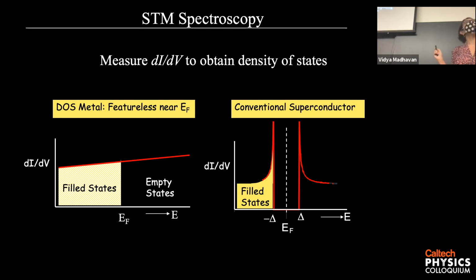For example, if you have a superconductor, we know that all the electrons are paired into Cooper pairs. So at low temperature, if you measure the number of states near the Fermi energy, you'll get 0. So at low temperatures, below the transition temperature, there are no states near the Fermi energy, and only above a certain value of energy do you start seeing states. So when we measure dI/dV in a superconductor, we get a sharp peak called the coherence peak at the gap edge, and then 0 density of states.